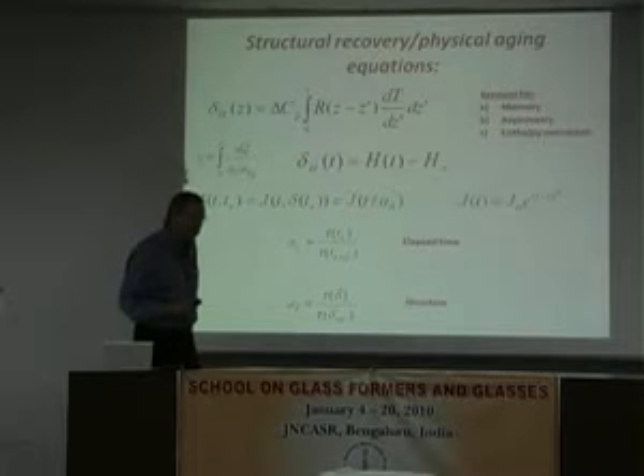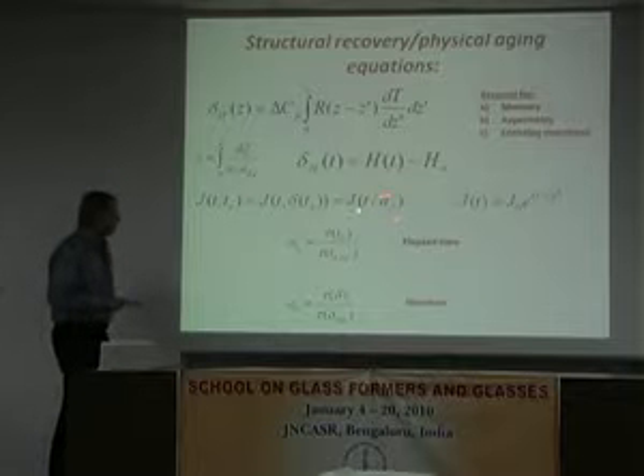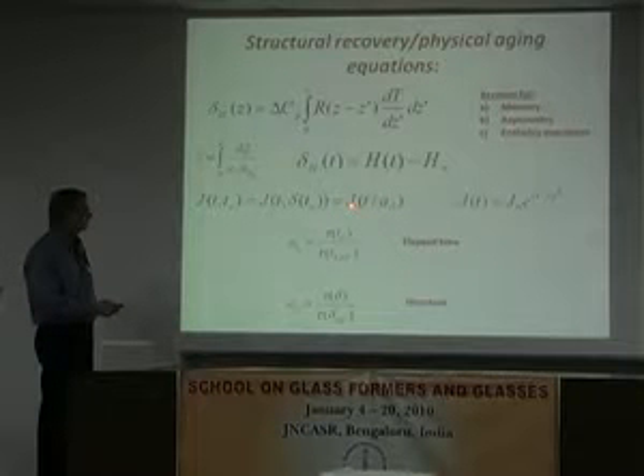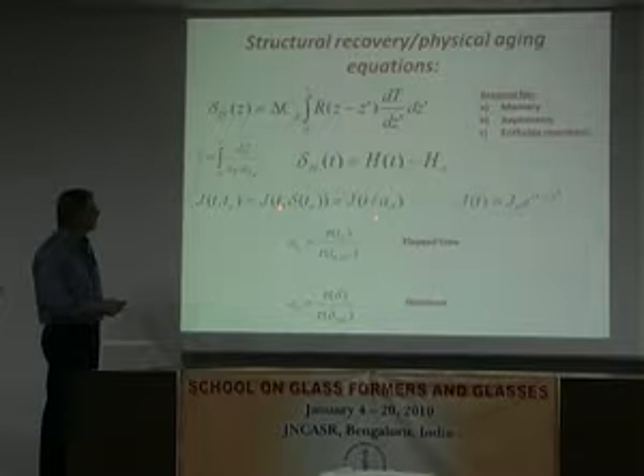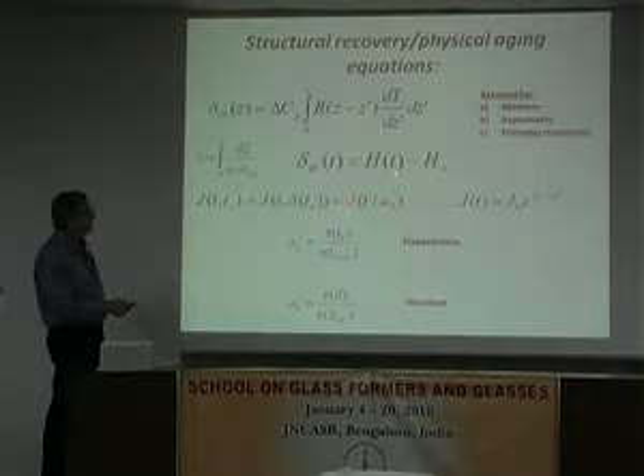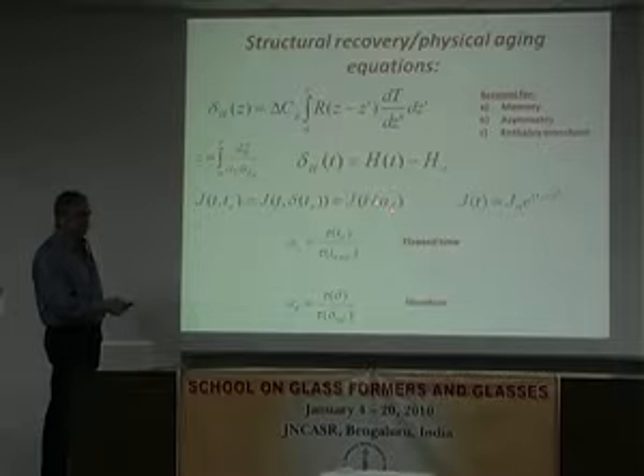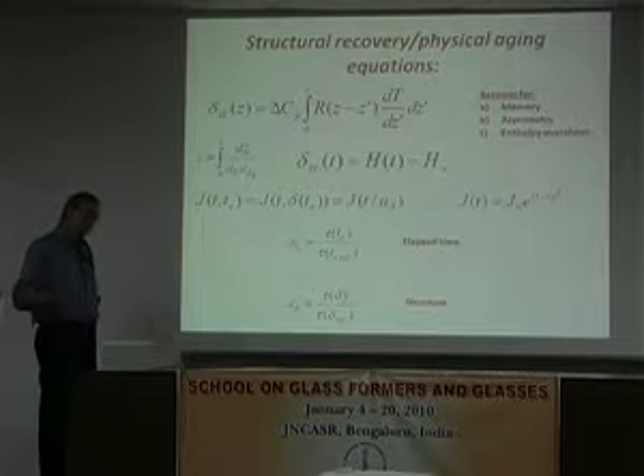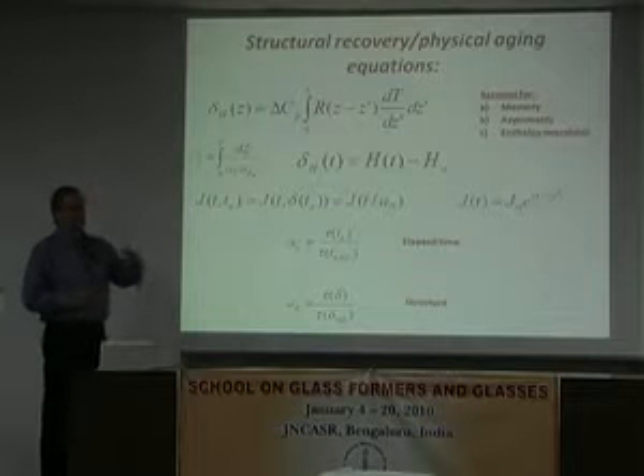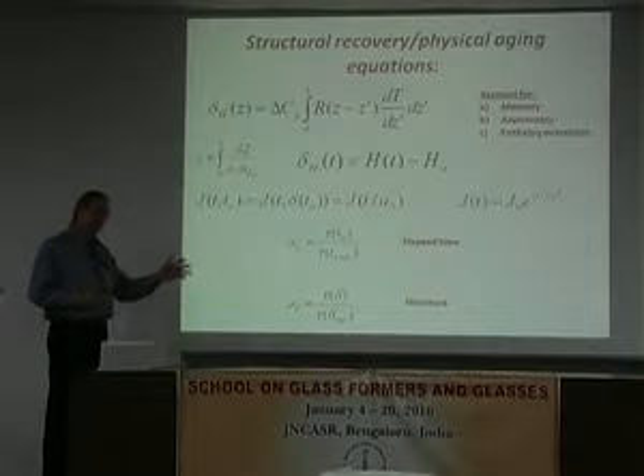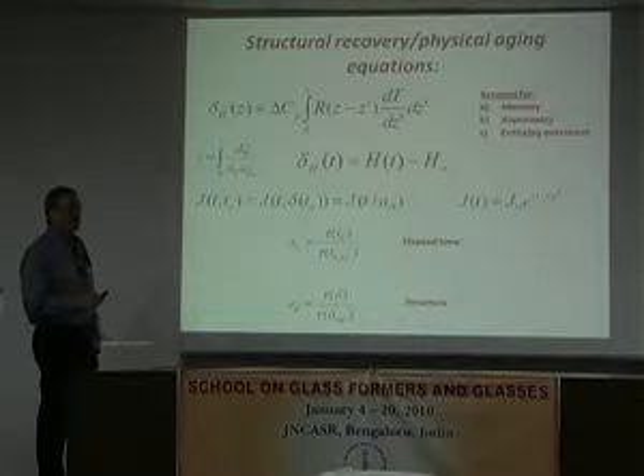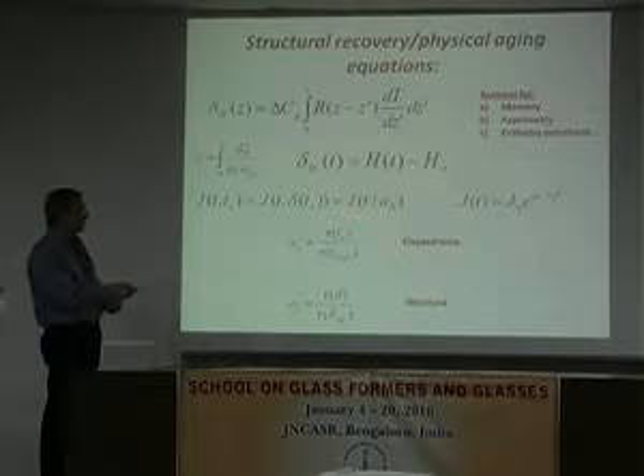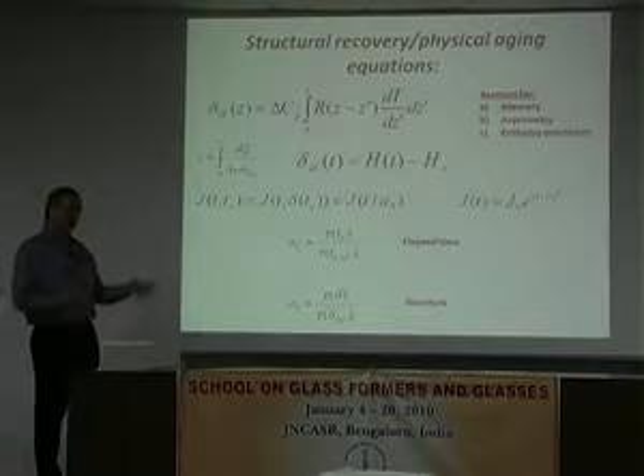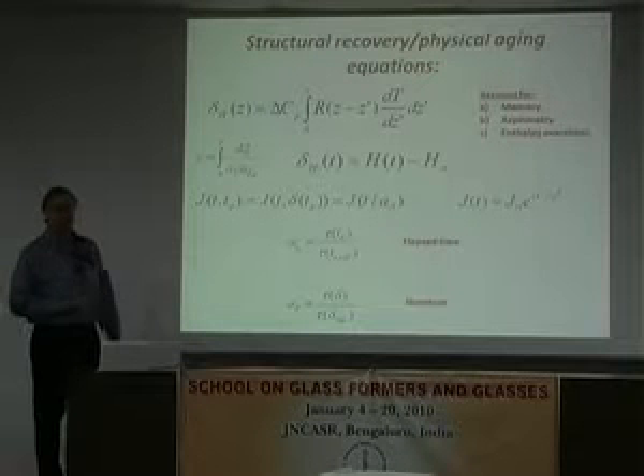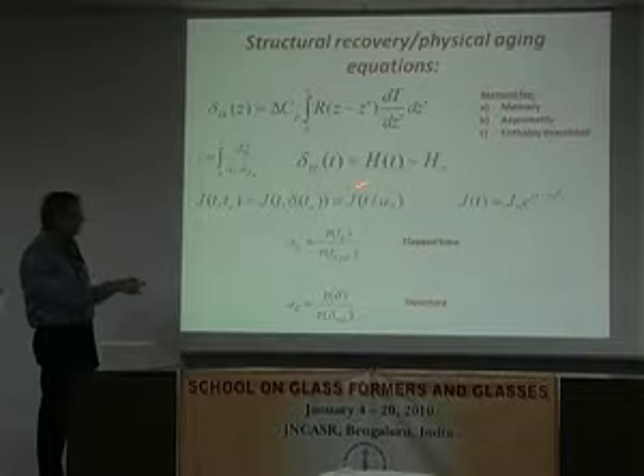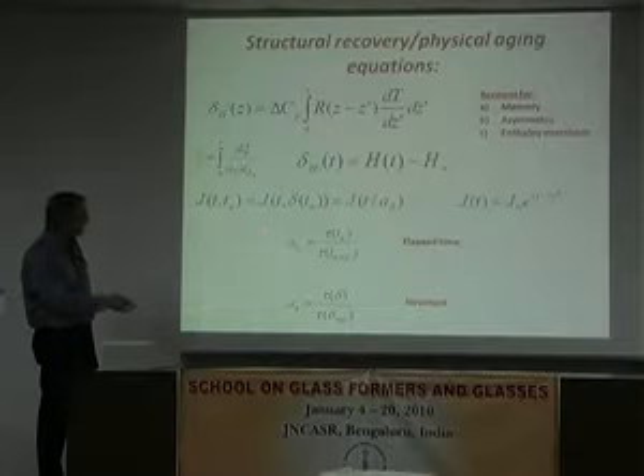I'm sorry? I'm not seeing something. So, that's a specific form. This? That two-time dependence, right? Well, this is a specific form of the dependence of J on the structure of the glass. It assumes that time-structure superposition is correct. And we actually observe that it's at least a very good approximation to correct. So it's an assumption, but it's an observation that seems to hold very well. And I'm going to show some data from Struik in a moment that shows that it's a very good approximation. But I do this, and if I do the elapsed time, I write it this way.